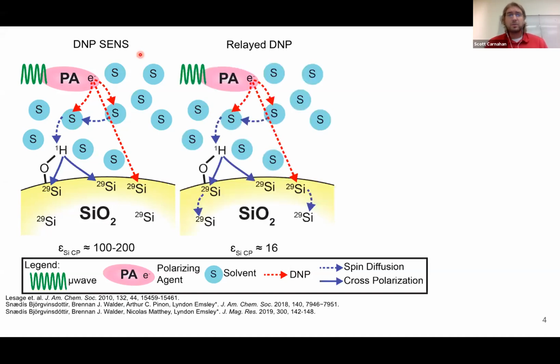More recently, the group from Lyndon Emsley has used that same technique to get polarization to the surface, and then use slow homonuclear spin diffusion to hyperpolarize the core of these materials. If you saw Sneha's talk earlier in the webinar series, she did talk about this a bit. Here they've been able to show this for silicon, tin, phosphorus, a bunch of different heteronuclei. But one thing you see is that the DNP enhancement that you get at the surface is significantly higher than you get for the core when you do this relayed DNP.